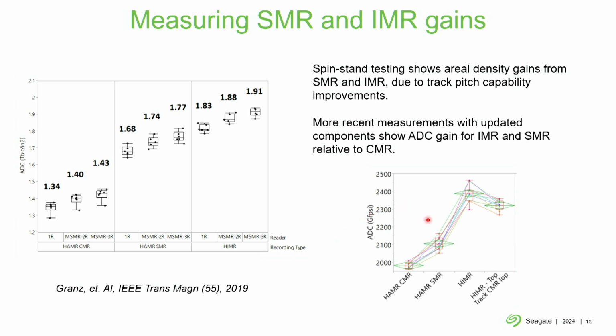And this is just newer data. So the older data, the max was 1.9 terabit per square inch, but in newer data, we're getting much closer to 2,500 gigabits per square inch, or 2.5 terabit per square inch. These are not demo numbers. These are heads run at more normal conditions.